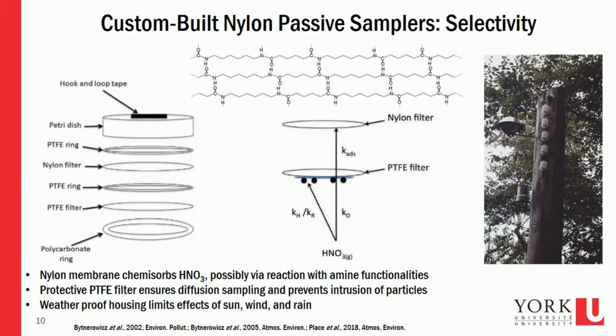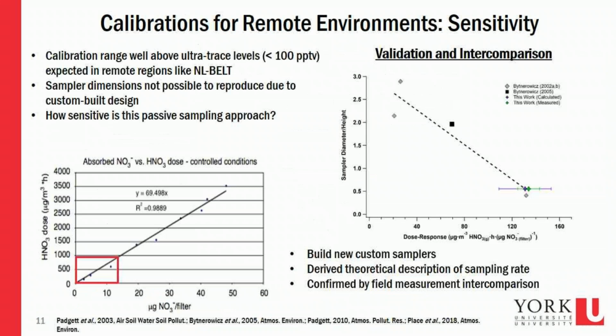We take our nylon filter, now that is selective, and we try to increase its selectivity further. So we sandwich it between two Teflon rings and protect it with a Teflon filter to keep out things like particulate matter that might deposit on the surface, other debris, any water that might be condensing if there's dew formation going on. And we sandwich this all together inside a petri dish, put it inside some fancy spray painted plumbing parts that we picked up at the hardware store, and create a nice weatherproof shelter in order to get quantitative collection over long time periods.